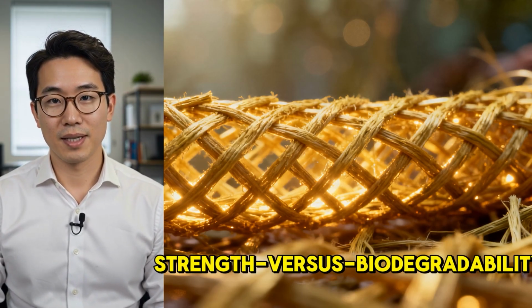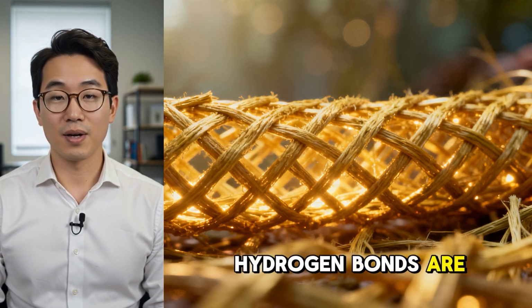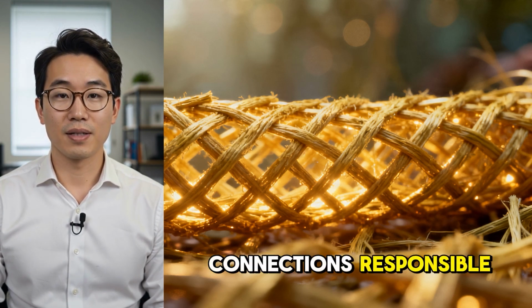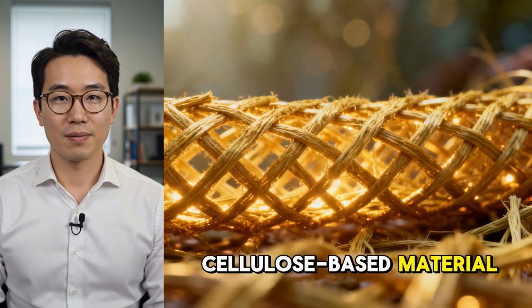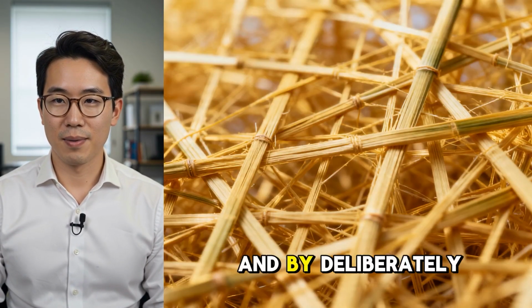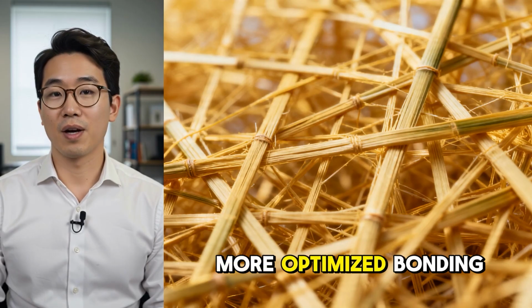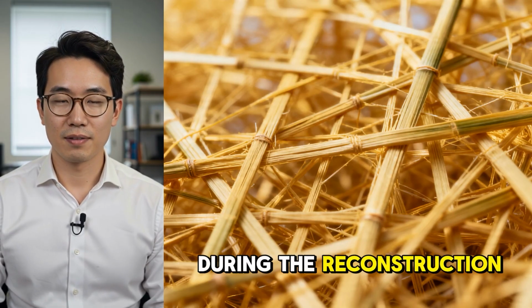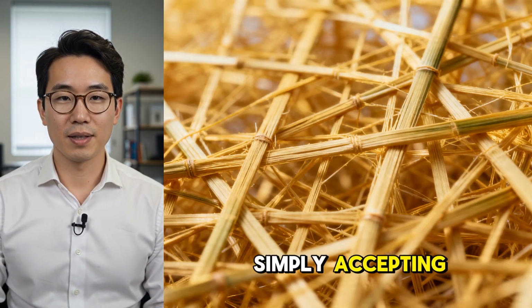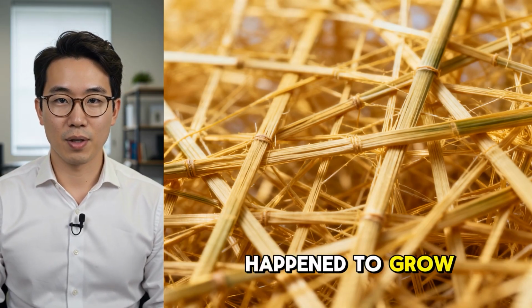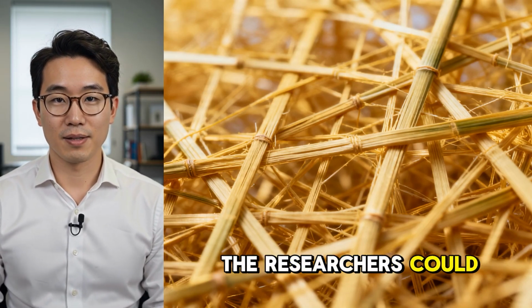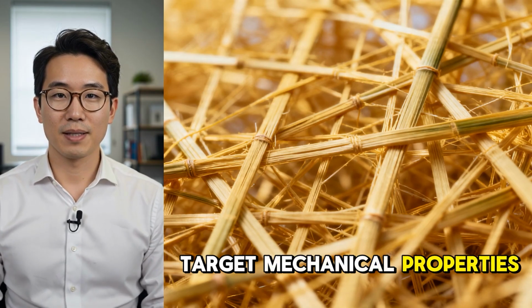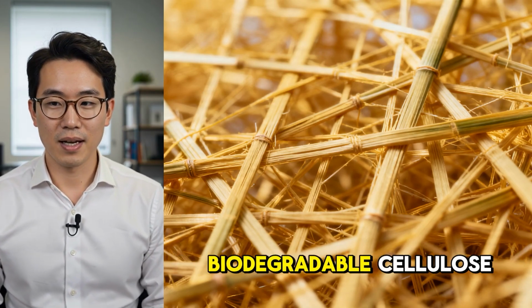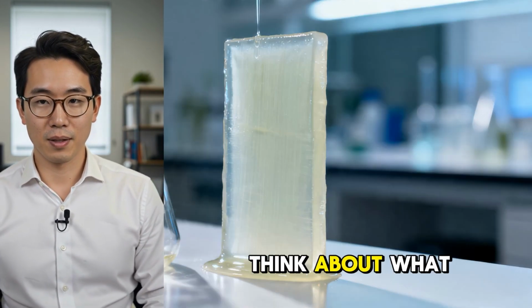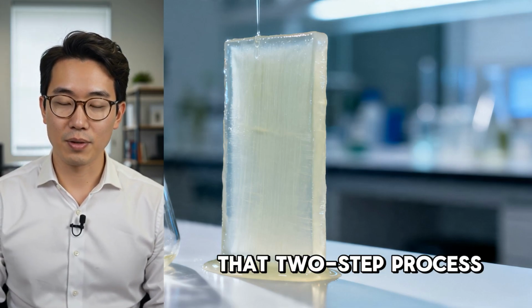versus biodegradability trade-off. Hydrogen bonds are exactly the microscopic connections responsible for holding any cellulose-based material together, and by deliberately engineering a denser, more optimized bonding network during the reconstruction phase, rather than simply accepting whatever structure raw bamboo happened to grow in naturally, the researchers could specifically target mechanical properties competitive with conventional plastic, while keeping the same fundamentally biodegradable cellulose chemistry underneath the whole structure.